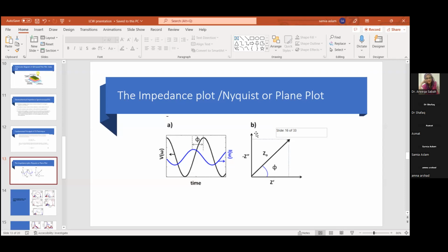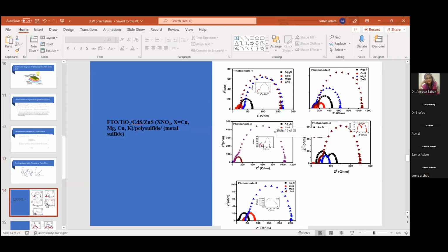This impedance plot gives the impedance at the interface, any interface, which can be between the photoanode and the electrolyte, or the electrolyte and the counter electrode. So it depends on how we are measuring the interface through the electrochemical impedance spectroscopy technique. So here I'm representing the results that I myself have conducted for a photoanode, and this is a schematic of the photoanode. The electrodes were prepared by the conventional wet chemical methods, which are reported in general for the solar cell, especially for quantum dot solar cell fabrication at laboratory level.